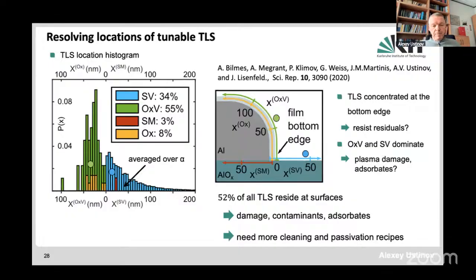So on the picture to the right, you see our system of coordinates. We have the origin here. And then we have, in red, the interface between aluminum, our superconductor, and the substrate, which in this case was sapphire, aluminum oxide, Al2O3. Then the yellow axis goes along the interface between metal and the oxide. And we know that because oxide has specific epsilon, so it's not vacuum, there is another interface between the oxide and the vacuum, which is the green surface there. And then the blue color stands for the defects located on the substrate-vacuum interface.